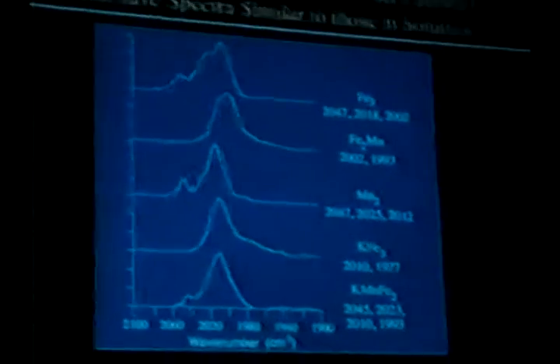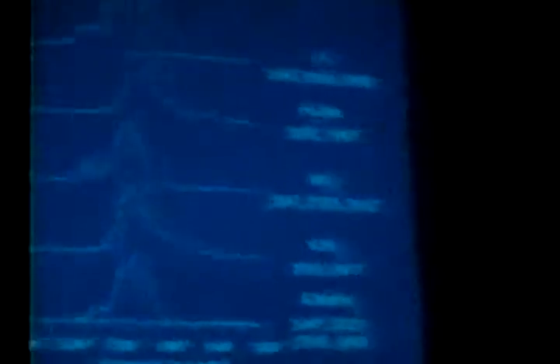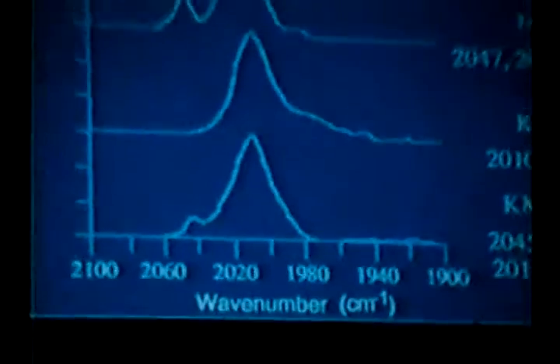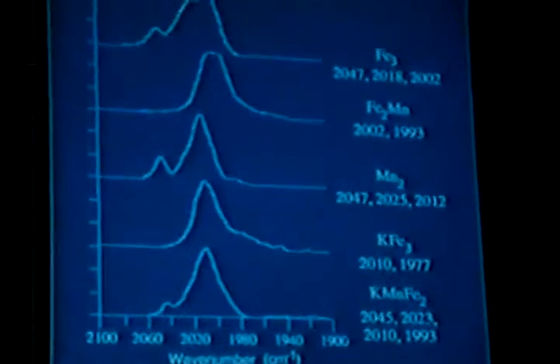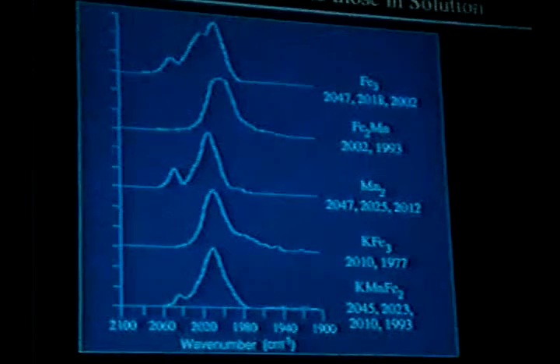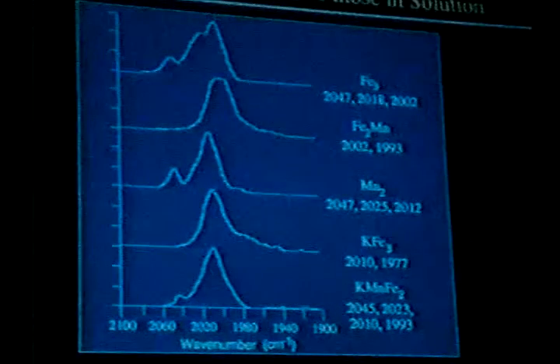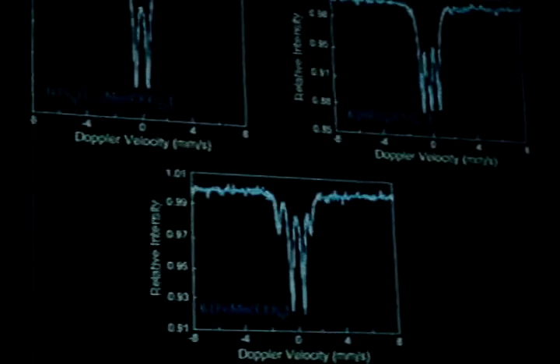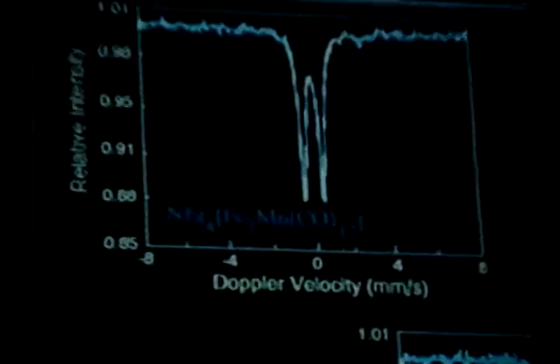I'm now going to discuss the physical characterization of these catalysts and try to relate physical properties to catalytic activities. We supported the catalysts on carbon and, for the first time, were able to look at the infrared spectra of these carbonyl clusters on carbon. Following impregnation, these clusters are intact — the spectra observed are virtually identical to those seen for these clusters in solution. Similar results were seen in Mössbauer spectroscopy, where the supported clusters retain their solution-like structures.